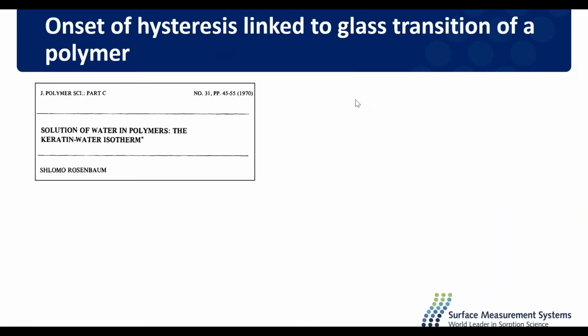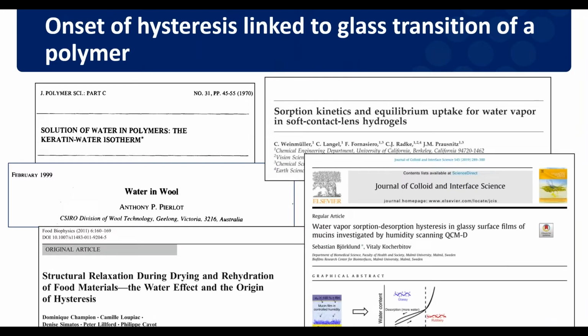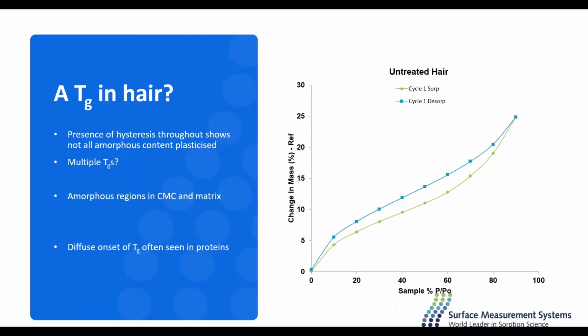So hysteresis has also been long shown to be linked to the glass transition of a polymer, in particular with a glass transition being linked to the presence of no hysteresis. Do we have a glass transition in hair? We've got hysteresis present throughout the whole water sorption isotherm, and so we cannot say that we have a sharp glass transition. And if we think back to hair structure, it's far too complex to have a single sharp glass transition point. Instead, we could say, as we see in other proteins, that there is a diffuse onset of glass transition events. And this is more likely with water plasticizing some of the amorphous regions in hair, allowing some glass transition events to occur, but not a full and sharp point.